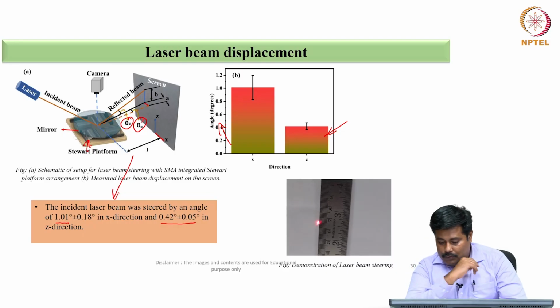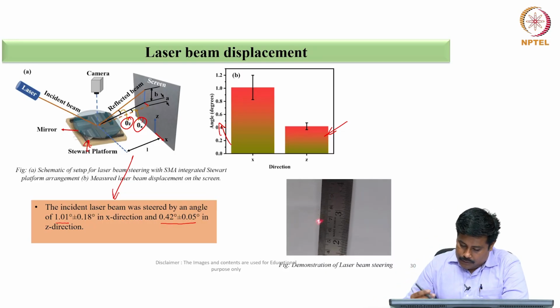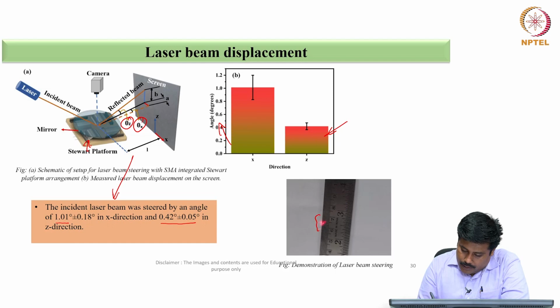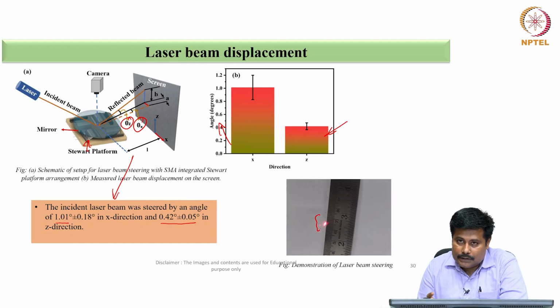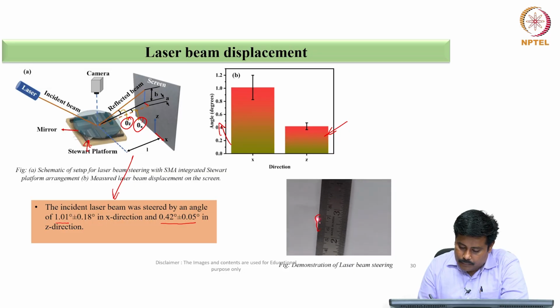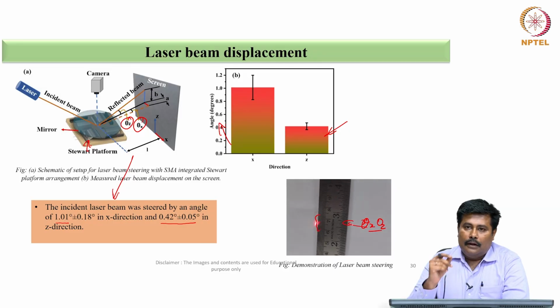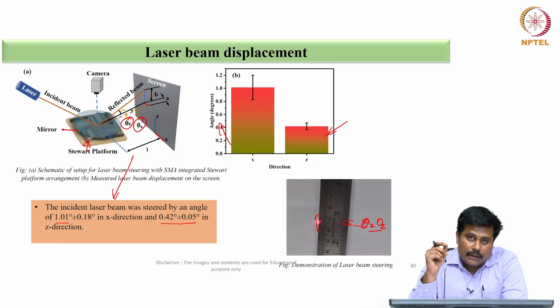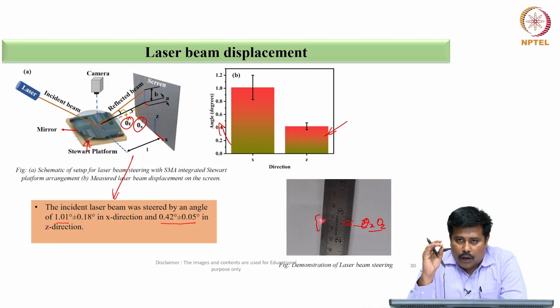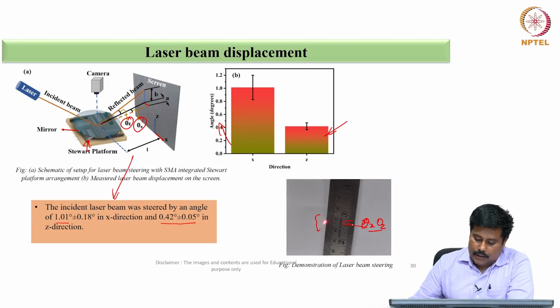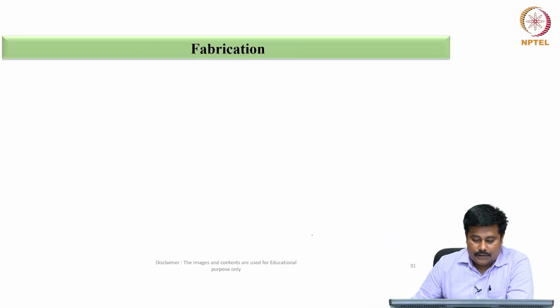So this is a closer view of the laser beam steering. If you closely observe, the overall deviation is well controlled, so there is no undulation in the system, and theta x and theta z are well recorded, and the overall micro manipulation is in the order of less than 100 micron, which is the observation here.